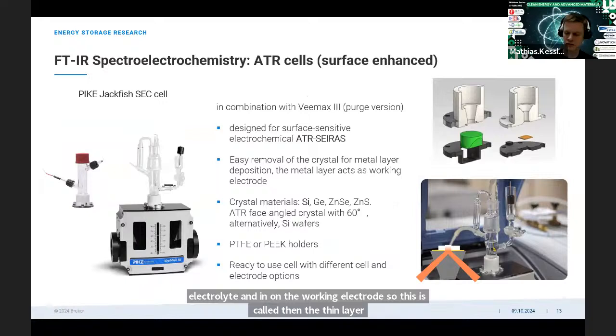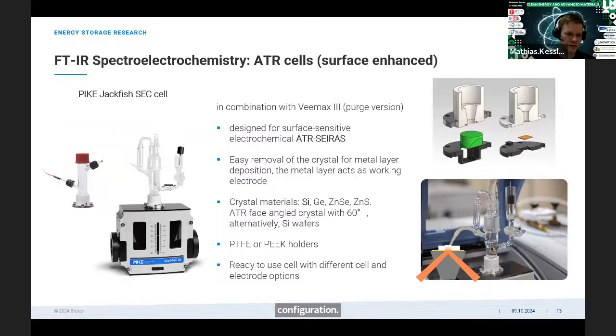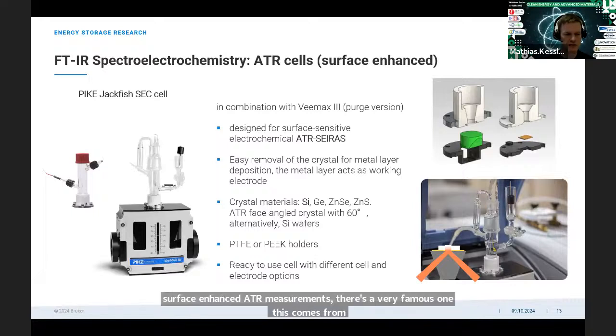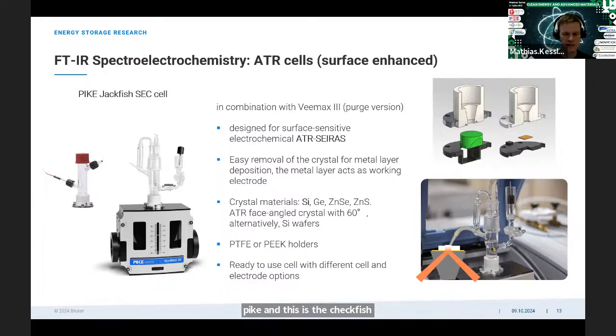There are also accessories available from other suppliers. For surface enhanced ATR measurements, there's a very famous one. This comes from Pike, and this is the Jackfish spectroelectrochemical cell. And this is also intended for surface sensitive ATR measurements, where we place either a silicon or germanium crystal inside, or we use silicon wafers. And again, these crystals or wafers are then coated with a metal layer which works as working electrode, and then we can do our surface enhanced spectroscopy measurements with that.